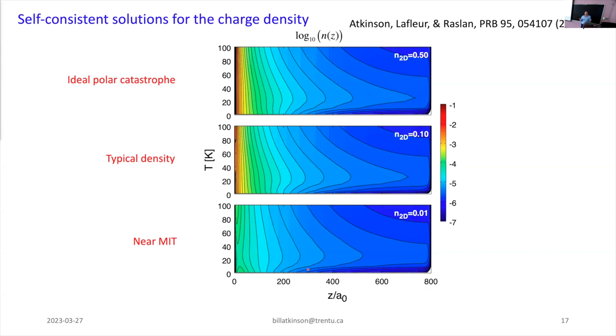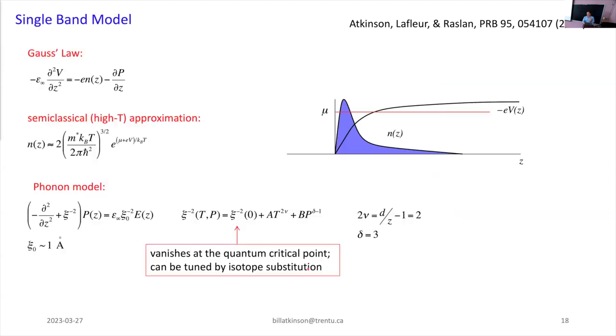And so that's what's pulling the electrons back to the interface. So that, in some sense, is not surprising. I don't think anybody had looked at the electron density like this before us, but the explanation is pretty intuitive. What's not intuitive is that this behavior can be traced back to the presence of a quantum critical point.